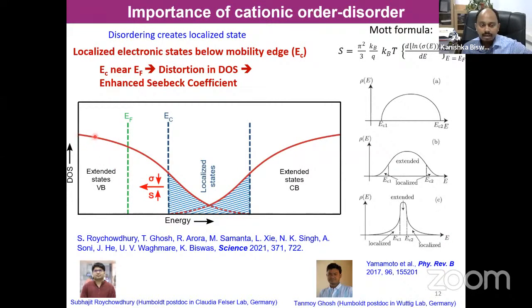If we have a valence band and a conduction band which are overlapping, this is basically a semimetal. As soon as I have, for example, silver and antimony disorder, more and more disordered, which is actually true in this compound, we have localized states. Okay, and these are the localized states, and these localized states are separated from the extended states by the mobility edge, a concept given by Mott, who got the Nobel Prize with Anderson in 1977. So this mobility edge separates the extended states from the localized states.